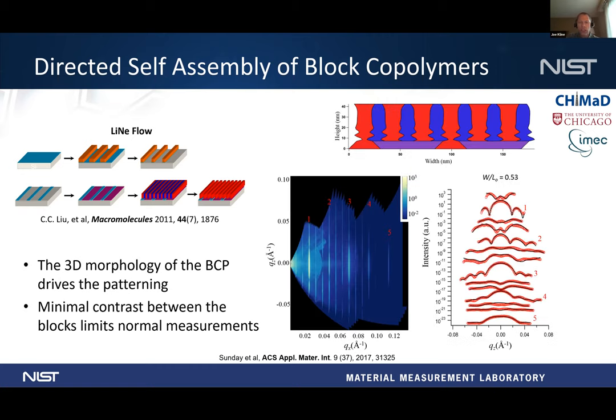And so this is showing an example of the CD-SAXS method that we did there. With hard X-rays, there's no contrast between PS and PMMA. And so this is at the carbon edge at 282 eV. And you can see there are quite a few scattering peaks that you get in here, versus if you do the hard X-rays, you only see maybe one or two peaks.